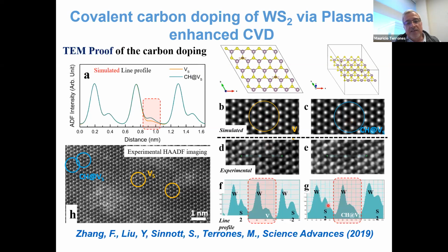And this is the line scan. So when you do a line scan, this is experimental. When you do a line scan, you have the vacancy of sulfur, it's like this. And when you see the CH at the vacancy, you see this pattern. So you can see there's a mild difference, and we can differentiate the CH groups from the normal vacancies. So this could be observed as well in the electron microscope.